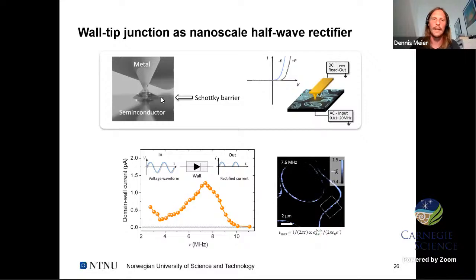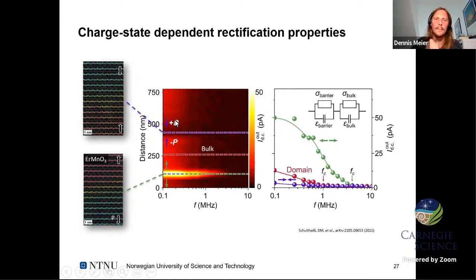We confirmed that then by doing the same measurements at positively and negatively charged domain walls. And you can nicely see here that the head-to-head walls, which are insulating, and the tail-to-tail walls, which are conducting, show these drop frequencies, the transition between rectifying and non-rectifying behavior, at different frequencies.